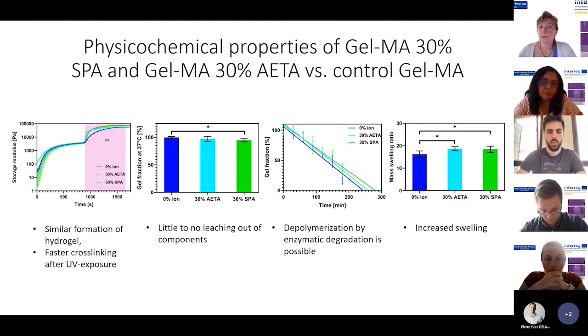Then we have also shown that these gels can be depolymerized by enzymatic degradation, and there is no difference between the three types of hydrogels that were tested. And there is a little increased swelling in the gels with the ions compared to the standard condition.